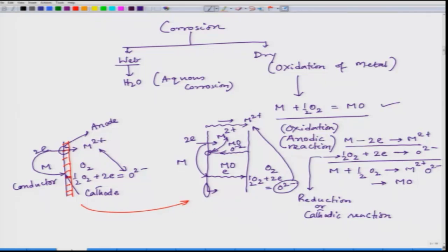Now, in case the metal ion is moving out from the metal and metal oxide interface and coming to the metal oxide and oxygen interface, and there it combines with the oxygen ion, then the oxide growth is taking place at the interface of metal oxide and gaseous oxygen. So, here also you are seeing that the condition of a corrosion cell is satisfied. That means we have a cathode and an anode. Since the cathodic reaction is taking place at this interface, this becomes my cathode, and this particular reaction is taking place at the metal and metal oxide interface, this becomes my anode.